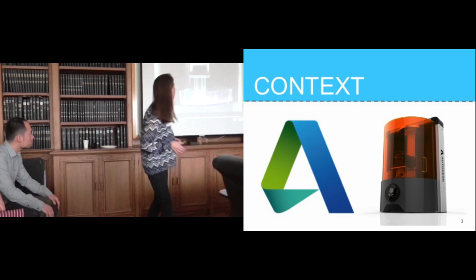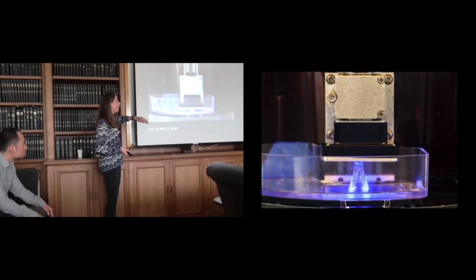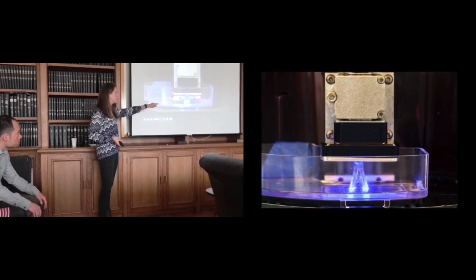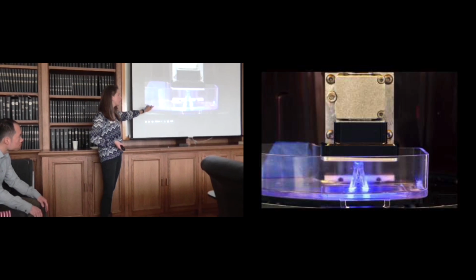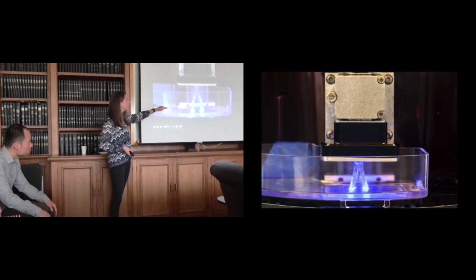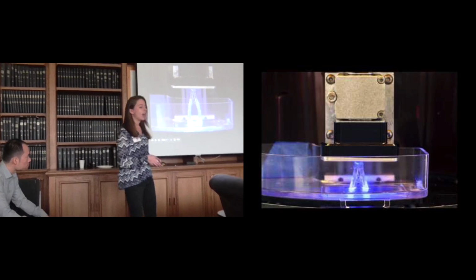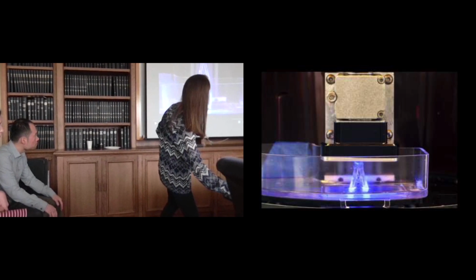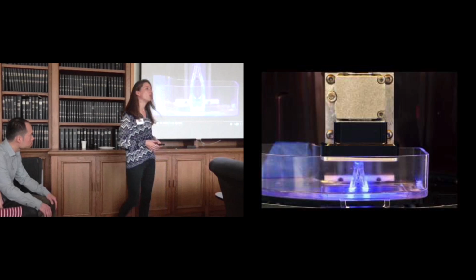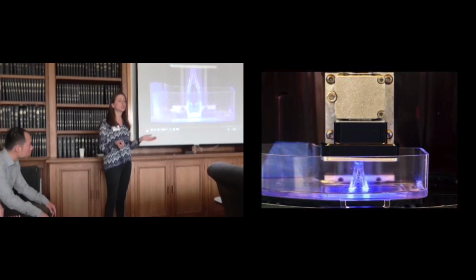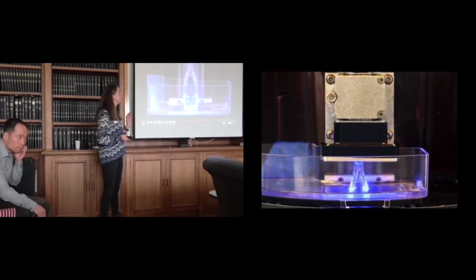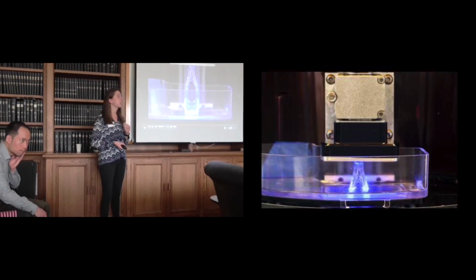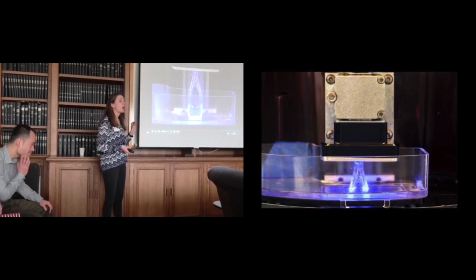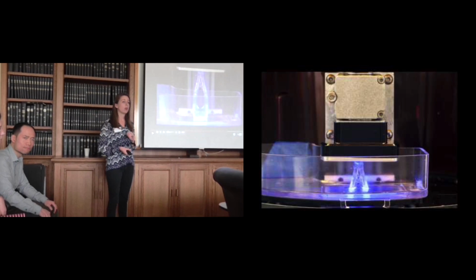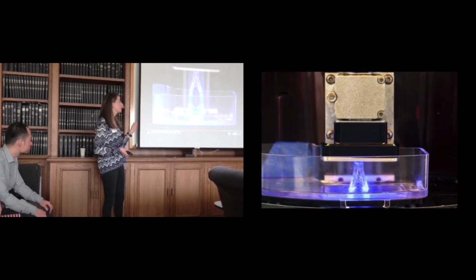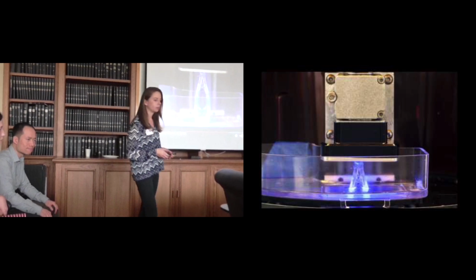What we have here is a time lapse. You see the build plate lowering, and from the resin tray, you can see the UV light there, and it's essentially converting the liquid resin in this resin tray to 3D printed objects. And if you notice, you can see pretty high resolution with this particular 3D printed object. That's one of the great features with SLA printing, and specifically with this Ember printer from Autodesk, is that they actually are able to have very high resolution with their 3D prints, down to 10 microns per layer in thickness, that allows for a great quality printed product.